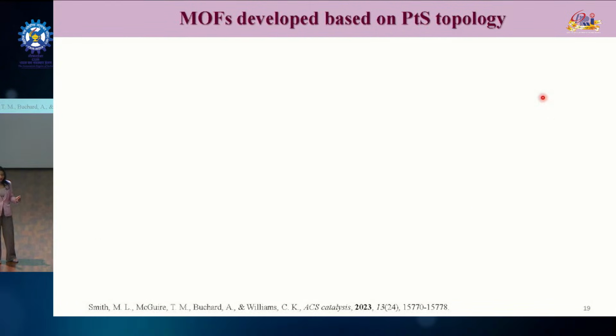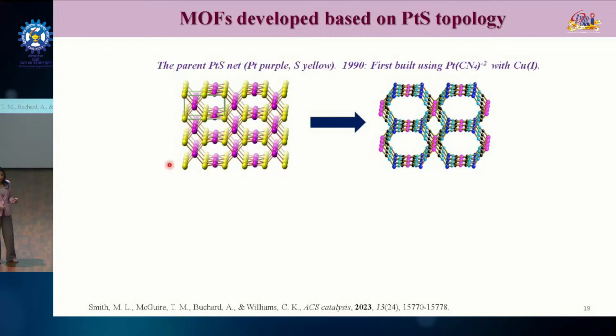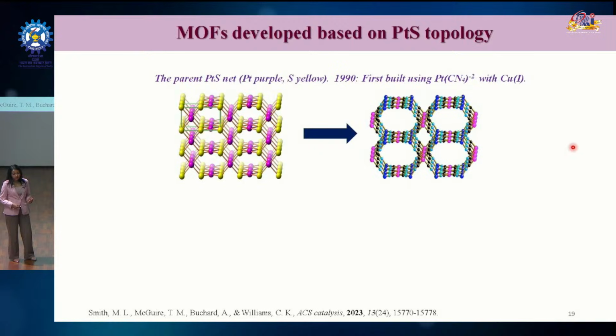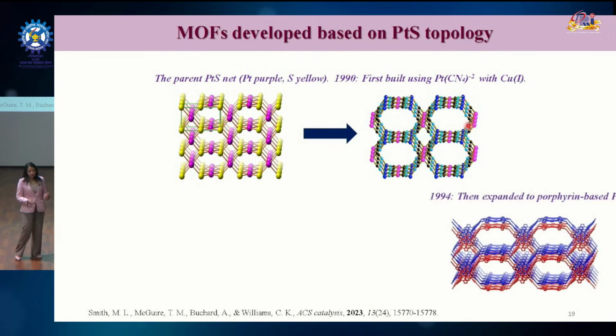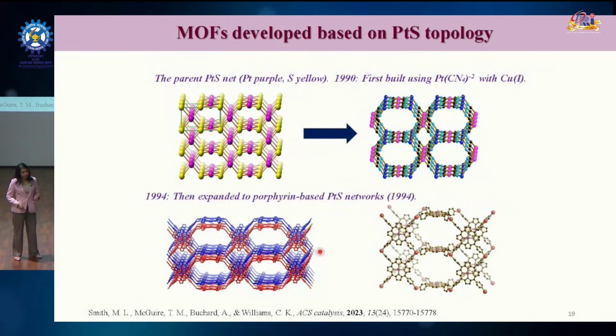After 4 years, he again got inspired by a natural mineral, the platinum sulfide topology net, and he mimicked exactly the same topology by replacing the platinum sulfide bond with a cyanide bond, and got a first porous layered framework. Then, moving further, because he was more interested in designing porous space, he replaced that cyanide bond with a porphyrin, because porphyrin has a larger length than cyanide, and he got the first framework with a large pore size.